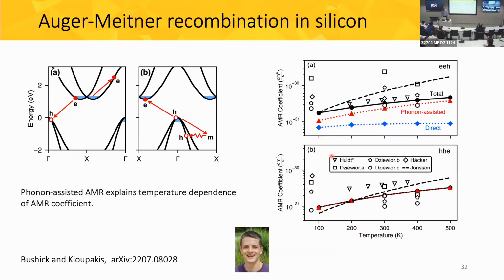We can also predict the dependence on temperature, and the challenge here is that we don't have good experimental data. The results vary over an order of magnitude, so it's hard to extract trends from experiments, but our theory is within the general ballpark of where experimental data should be.